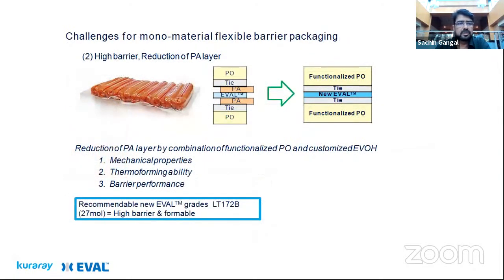Maybe a structure not relevant to India because we are talking of meat packing, but just as an example, again, nylon or a polyamide-free structure where we have a new generation of EVAL, the lowest ethylene content, 27% ethylene content, to get the mechanical properties. Again, the mechanical properties we assume would be met by the functional polyolefins, the metallocene polyolefins, the thermoformability, and the barrier performance. Next slide, please.